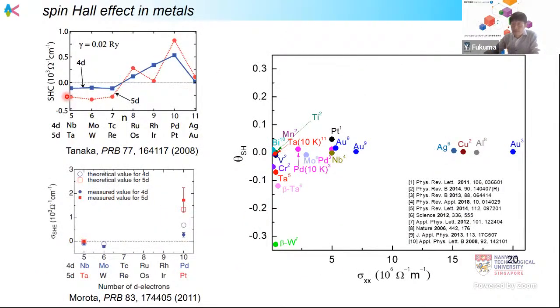So this is the prediction of the spin Hall effect for the 4D transition material and the 5D transition material. It's theoretical work. What we can see here is, compared to 4D, of course 5D has the stronger spin orbit interaction. That's why we can increase the spin Hall effect. And also here the sign of the spin Hall angle is changed from negative to positive. This is due to the total spin angular momentum. On the negative side it is less than half of the momentum, and here it is more than half of the momentum, so the sign changes.